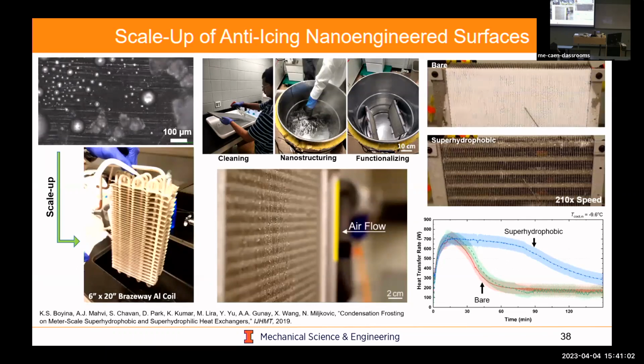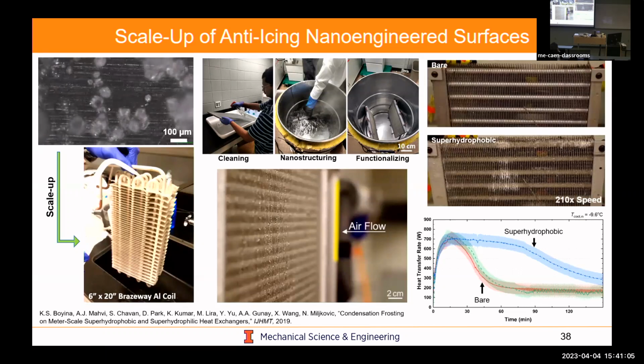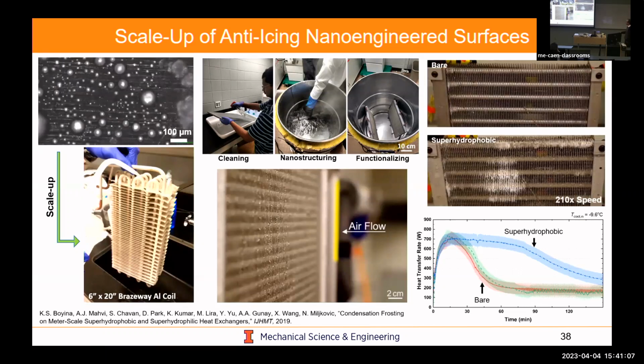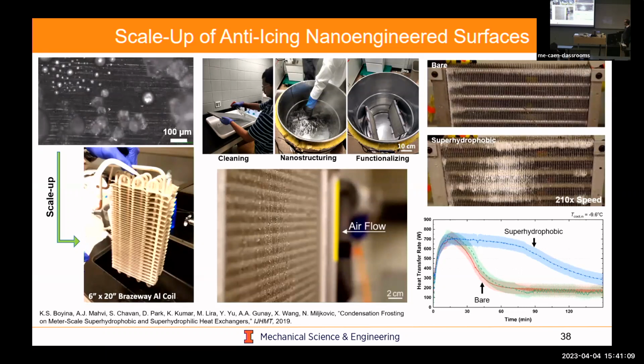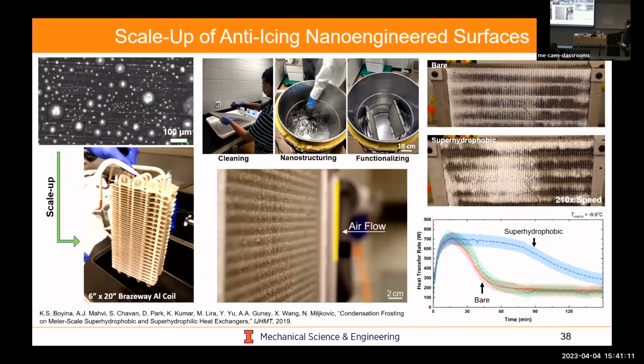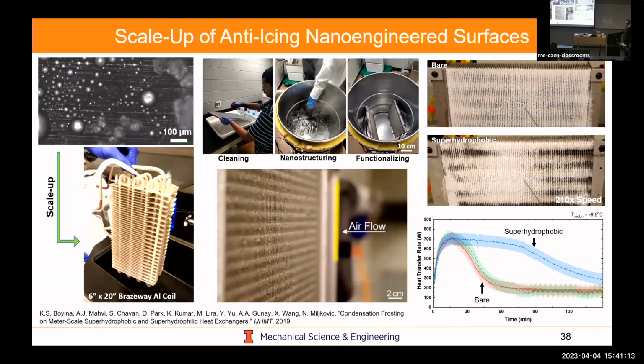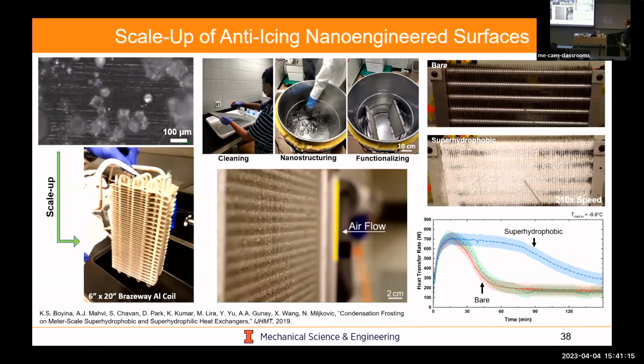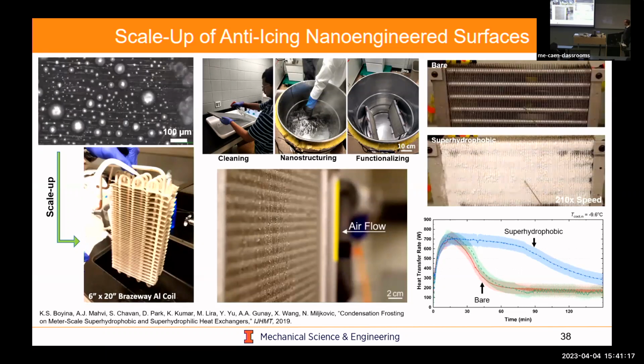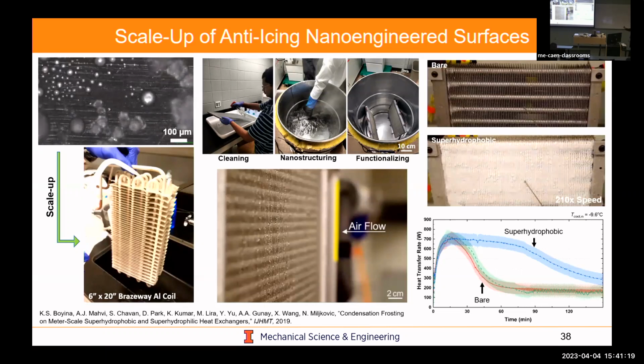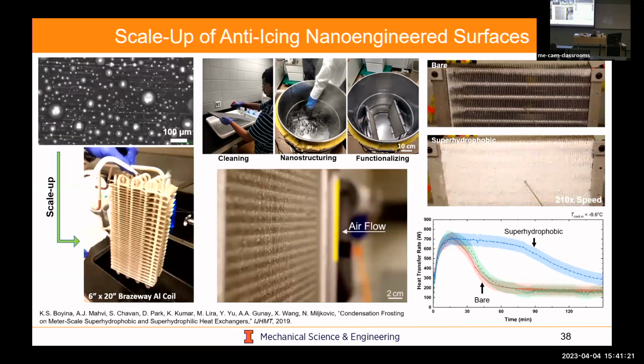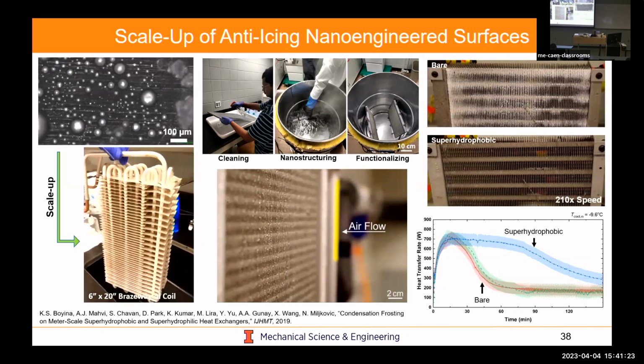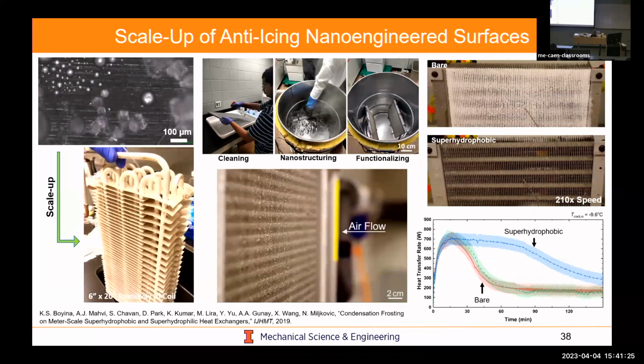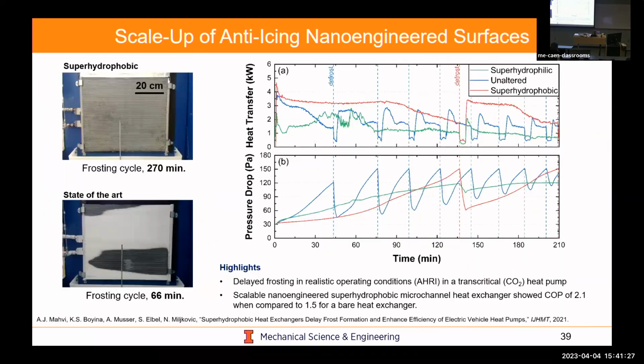And so what you could do is delay your de-icing cycle and save yourself efficiency. You can see here, if you plot the heat transfer rate as a function of time, your super hydrophobic heat exchanger maintains its performance over a much longer time compared to your super hydrophilic one or your bare one. And so again, that's more fundamental, but as we go to real demonstration, this is a demo of the super hydrophobic heat exchanger on a